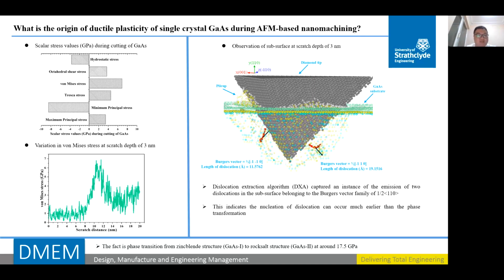Here, the atomic stress tensor was averaged temporally and then processed using an established 3D stress mechanics theory, as shown in this figure. It's evident that the magnitude of von Mises stress in the cutting zone was around 7 GPa, which appeared close to the experimental nanoindentation hardness of gallium arsenide. So the result shows that both the von Mises and the minor principal stress criteria can be used to predict yielding during ductile mode cutting of gallium arsenide. The fact is, the phase transition from zinc blende structure to rock salt structure is around 17.5 GPa. Therefore, we can conclude that phase transition is not happening.